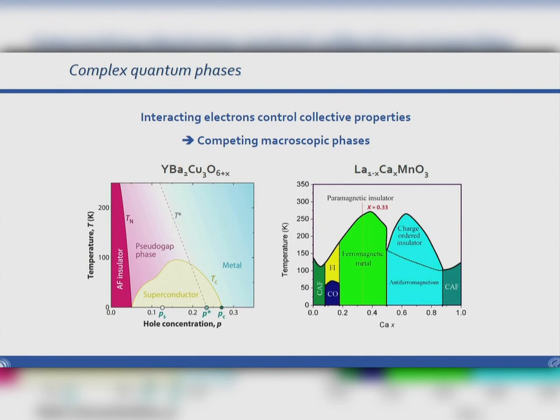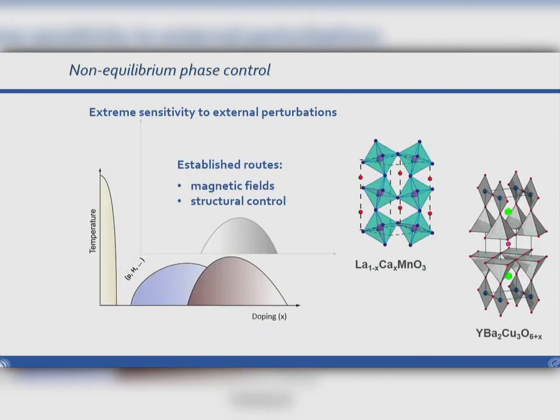Another system that you might be more familiar with is this magnetoresistive manganite, where you see that by changing the concentration of some certain atoms, you can choose in which magnetic phase you will localize. What these systems have in common, though, is that they are extremely sensitive to external perturbations. For example, magnetic fields and structural control. And what you, of course, know is that if you apply a magnetic field to such a manganite, you will end up with colossal magnetoresistance, changing the resistivity over orders of magnitude. Applying pressure, for example, to such a high-temperature superconductor would change the critical temperature. So here, the structure is more important.